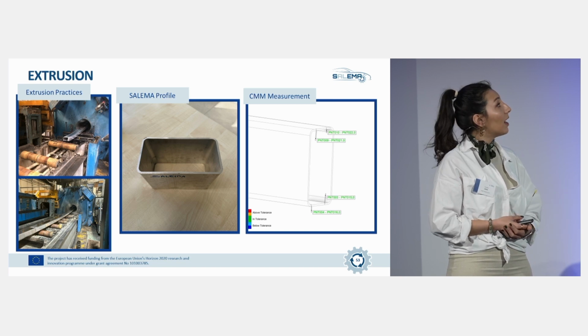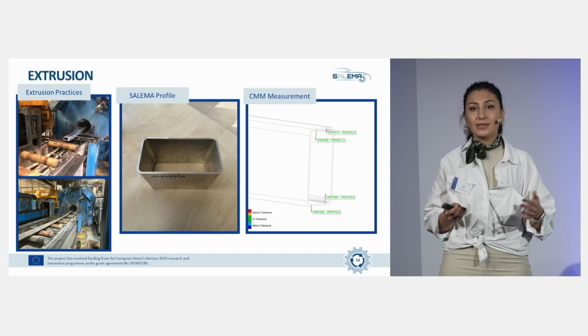After that, all of these profiles have been measured in the CMM measurement in order to be sure whether this SALEMA profile, which will in the end be welded to the high pressure die cast part to create the frontal frame, has tolerances and geometry that are okay or not.